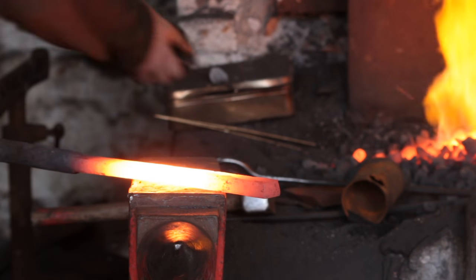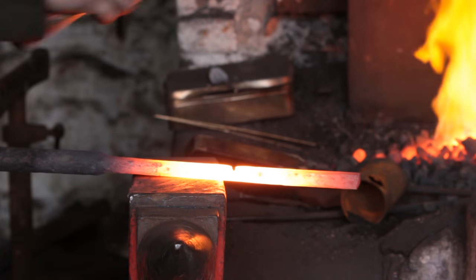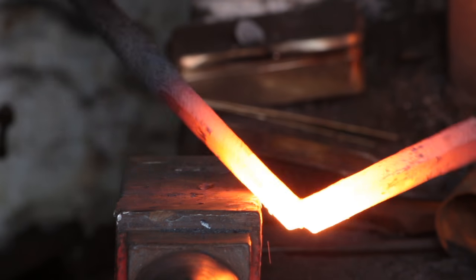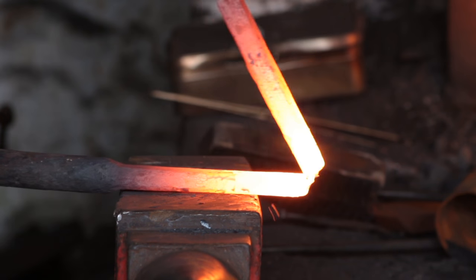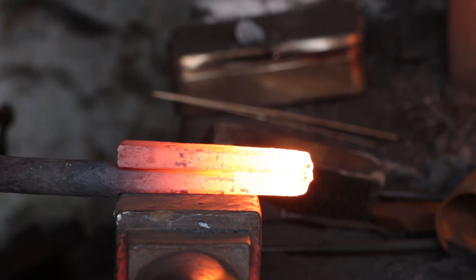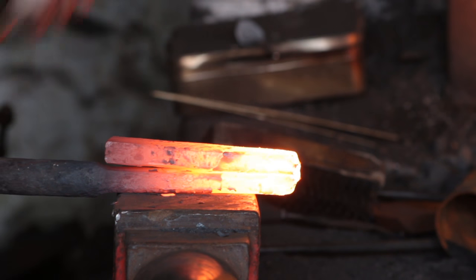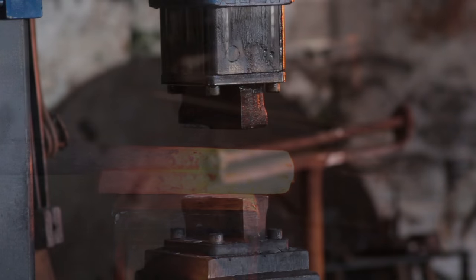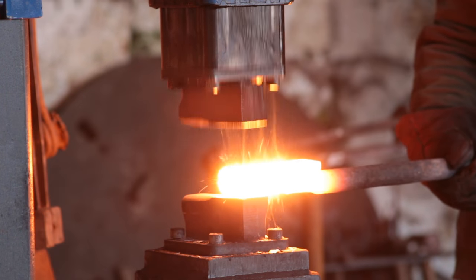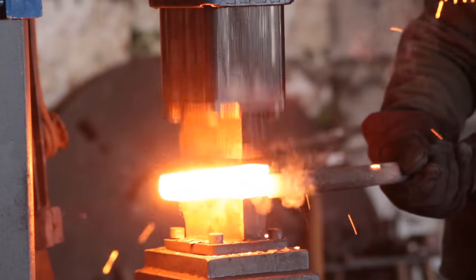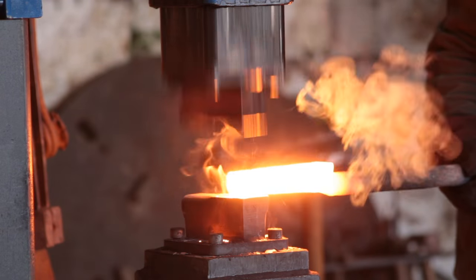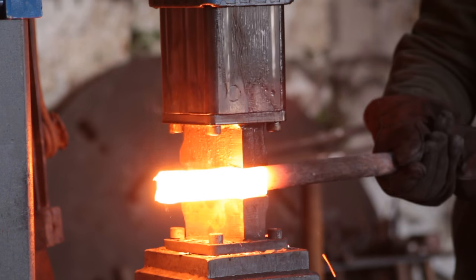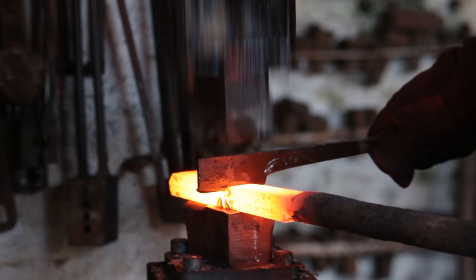Wrought iron's quite nice for welding because of the silica and slag content. It tends to be self-fluxing, in that the silica contained in the iron will form a protective layer around it. So you do actually get it hotter than mild steel for fire welding it as well.